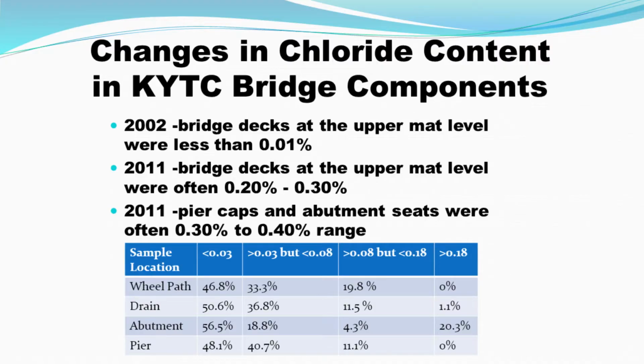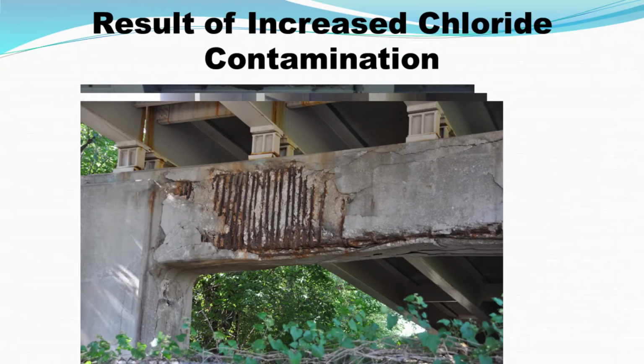The pier caps, almost 50% of them were around the 0.03 range, and 40%, almost 41%, were in the 0.03 to 0.08 range. Again, this just shows the leaking joints truly provide the pathway to deterioration of the concrete. Here is simply a picture showing spalling of concrete. We've all seen lovely pictures of those, and we drive under bridges all the time that look like this.